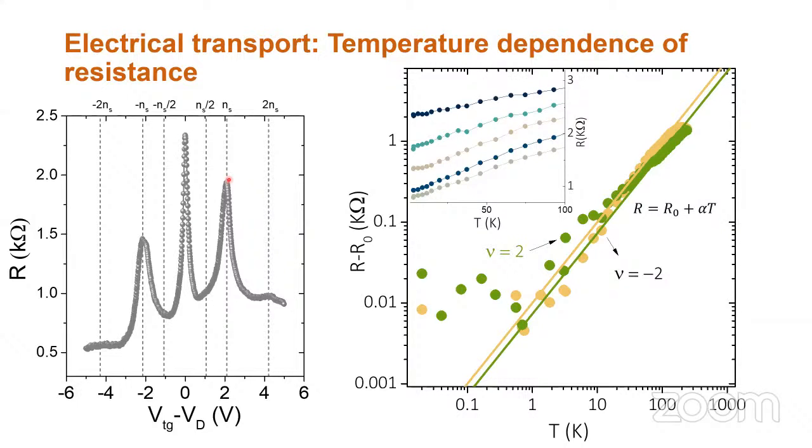What's interesting here is the temperature difference. In a standard magic angle device, where the misorientation angle is 1.1 or so, there is a strong peak, which I'm going to show you later, even at half filling. But at 1.6 degrees, where the correlation effects are supposed to be weak or non-existent, we do not know, there is no additional peak here. If you look at the temperature dependence, it's essentially linear.